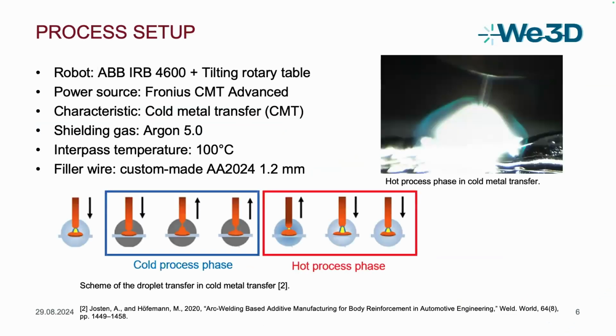Anyway, we did it, and we used the ABB robot with the tilting rotary table for the processing, Fronius CMT power source with the characteristic cold metal transfer, or CMT in short, argon as the shielding gas, and the interpass temperature 100 centigrades. As mentioned, these wires are very hard to process, therefore they are not available on the market, and we had to produce our custom-made wire by ourselves by hot extrusion.